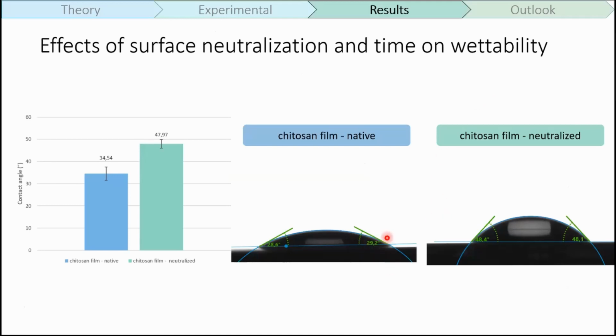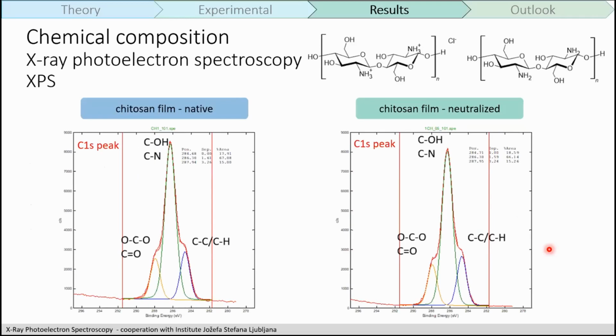As you know, if the water contact angle with your surface is quite low, this means that the surface is very hydrophilic. In the case of the Chitosan native film, the contact angle was rather low. After the neutralization step, the contact angle got to about 50 degrees, which gives us a surface that's not so much hydrophilic afterwards, but still hydrophilic.